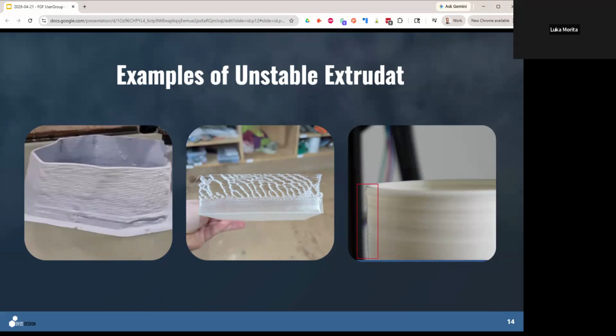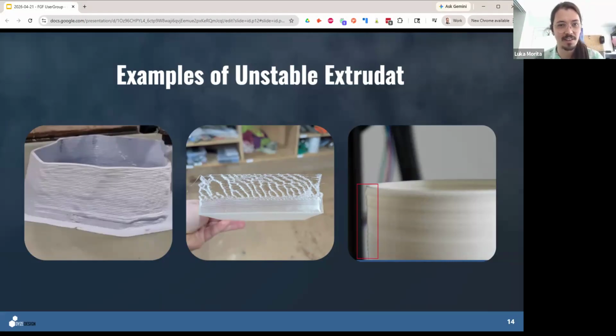I was wondering actually if I could hop in with a comment here about the air gaps. Over the summer, I was using FGF to print soft robotics, so pneumatically airtight components that could move when they were inflated. And maybe to echo Tosin's comments, I was having really notable issues with printing airtight components because of the interlayer voids that would be left behind between printed beads, and we had to do a lot of iterating on the aspect ratio of the printed bead in order to try to eliminate those gaps so that we could prevent leaking.